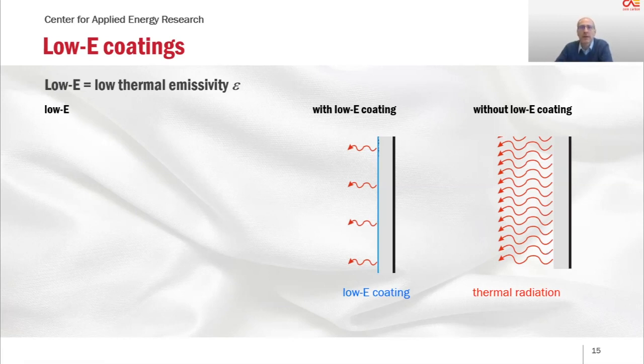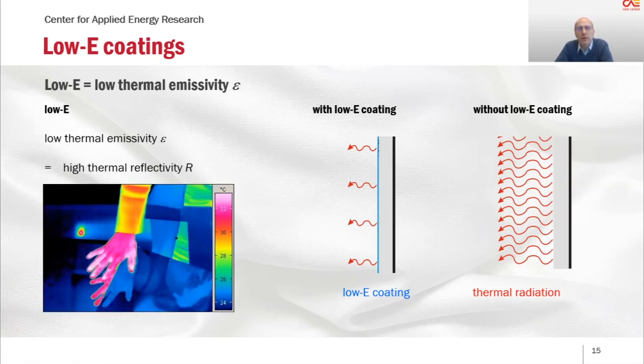amount of thermal radiation. Additionally, the low emissivity equals a high thermal reflectivity R, which has been demonstrated by Oliver Zech already in the video, and which can be seen here on the infrared thermogram. So here on the right, you see a glass sheet without low E coating, and on the left, you see the glass sheet with low E coating, and the heat from the body, or from the hand in this case, is reflected by the low E coating, whereas the reflection without low E coating is significantly lower. That means the silver nanowires reflect thermal radiation and therefore emit a low amount of thermal radiation into the surrounding.